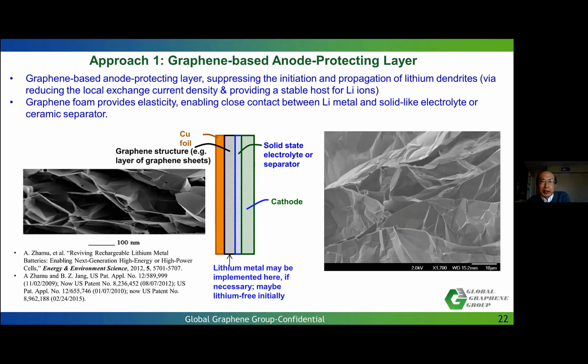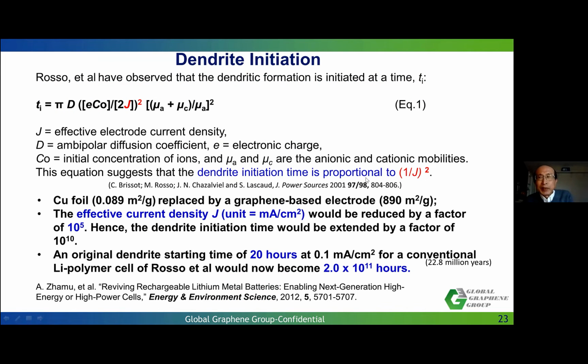Let me very quickly explain this. We published a paper in Energy and Environmental Science, so I'm not going to go into the detail. In short, by implementing our graphene sheet in an anode, we significantly increase the specific surface area of our anode. Because of that, the so-called exchange current density, J, will be significantly reduced. The dendrite initiation time is inversely proportional to J squared. So if you reduce the exchange current density, you essentially increase the time required to initiate the dendrite to almost infinite.